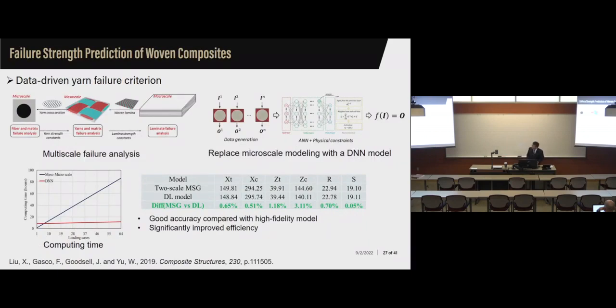And this example shows that usually, when we do woven composites, we assume something for the yarn. We try to get the failure criterion for the yarn. Usually, it does not exist. So if you really want to do multiscale modeling, you are based on fiber volume fraction to get the yarn properties, then do the global analysis and apply a certain load, right? Then go back at each Gaussian point into the micro level to figure out the stress concentration to see whether the fiber or matrix or the interface failed or not. If not, then you increase the load at the woven fabric level and do it again. Then later you will find the failure status of the woven fabric. That's clearly a very computationally extensive process.